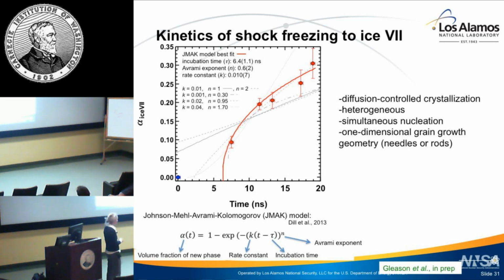So here I'm showing this expression commonly referred to as a JMAK model, or the Johnson-Mehl-Avrami-Kolmogorov model. Starting in the late 1930s, this was applied to melt quench experiments to look at the kinetics of the phase transitions that were taking place. So here we're trying to apply this very simple functional form to the data that we're getting on shock compression. And here I show my best fit. The incubation time, or the time it takes to seed and grow a new ice 7 crystal, is something like 6 nanoseconds. That seems quite fast for a disorder to order transition, right?